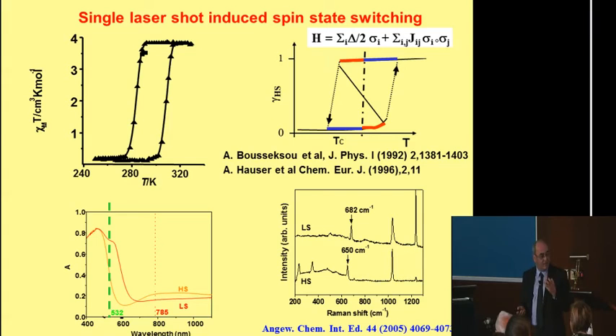If you analyze the hysteresis loop through the Ising-like model, like I showed you before, you see that if the interaction is strong enough, you have a hysteresis loop. What is very interesting to see here is that around the Curie temperature here, you have 4 regions, okay? You have 2 metastable regions in red here, and 2 stable regions here. Here you have the high spin form, here you have the low spin form. Because you have 2 metastable regions here with different spins, when you are in a metastable state, if you apply any pulsed energy, you can push the system to go to the stable one.